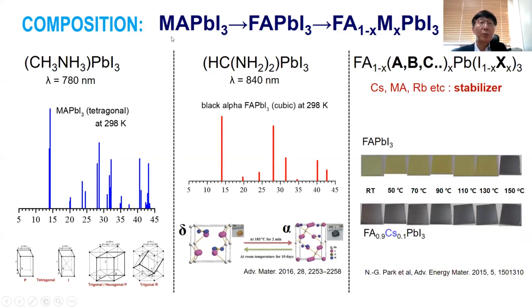Regarding composition, we start with MAPbI3. However, as I mentioned, FAPbI3 is better than MAPbI3 in terms of the light absorbing property because of narrow band gap energy, and therefore the absorption can extend to 840 nanometer as compared to 780 nanometer for MAPbI3. However, FAPbI3 is quite unstable at room temperature. The alpha phase transforms to the delta phase at room temperature. Therefore, it is necessary to stabilize alpha phase FAPbI3. In that case, if you use the cesium or methyl ammonium cation, then you can easily stabilize alpha phase FAPbI3 even at room temperature.